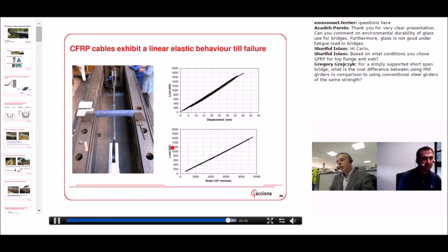And probably it is still higher than the cost of steel if you look at the initial cost of the bridge. But if you take into account the entire life cycle cost of the two solutions, you have a surprise, because you have to paint your steel bridge many times to maintain it, while this is not necessary with the same frequency for the FRP bridge. So if you have an FRP bridge with a concrete deck reinforced with GFRP rebars, from a life cycle point of view it is much better than a steel solution, even if the initial cost is a little bit higher.